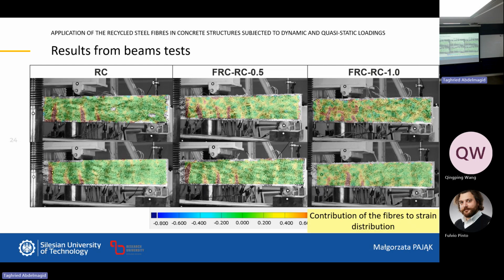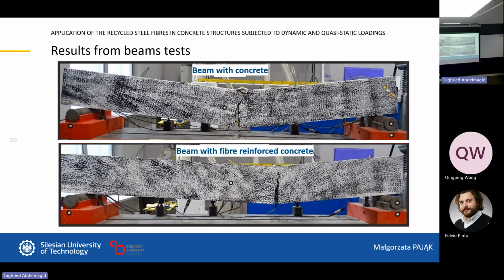So, the contribution of the fibers, we notice the contribution. You can see it here, the difference between the beam without the fiber and with the huge amount of fibers. However, it didn't change the parameter that is used in calculations. So we can't say that the fibers decrease the number of the cracks. So it's not too good. In truth, it's not too good.